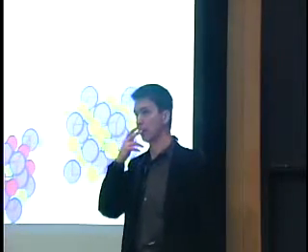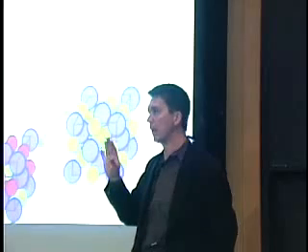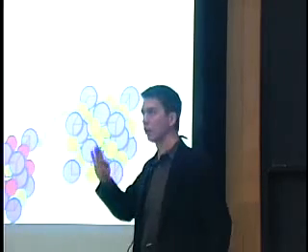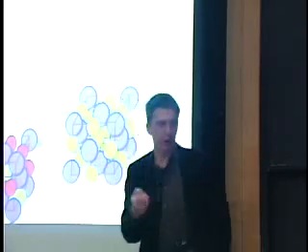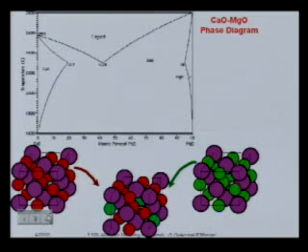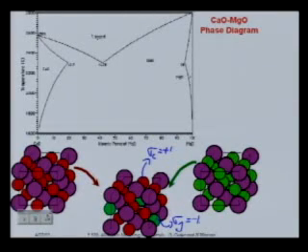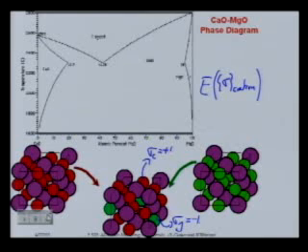It's a lattice model. But this already illustrates a nice thing about this approach. In your whole lattice model, the oxygens won't appear. The variables you use are only going to be defined on the cation lattice. The cations are the smaller ones. So on this one, you'll have sigma_i is, say, +1, and on this one, you'll have sigma_j equals -1. So you're going to express the energy solely in terms of spin variables on the cation sites.